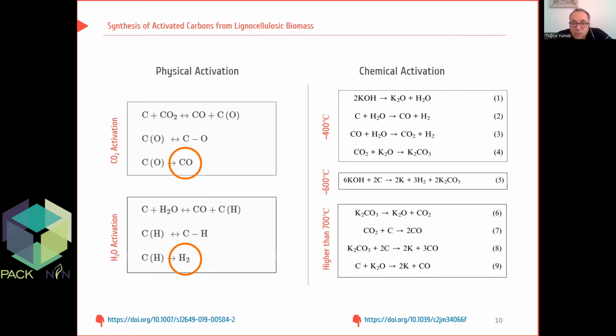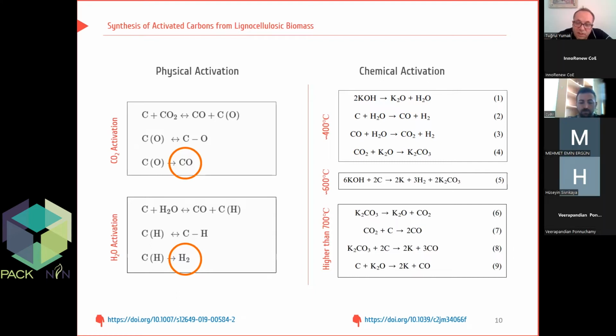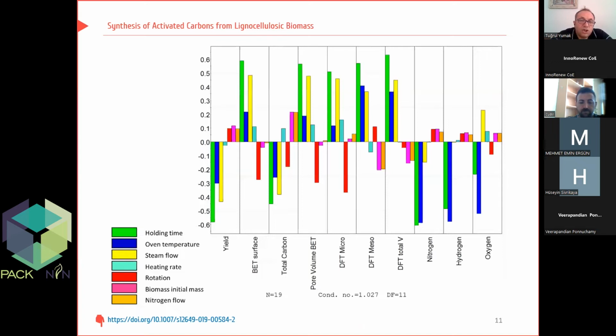The potassium compounds, potassium oxide and carbonate, also can be reduced by carbon to produce metallic potassium at temperatures over 700. So, two different reaction pathways both resulted in an increase in the surface area and the development of the porous structure.